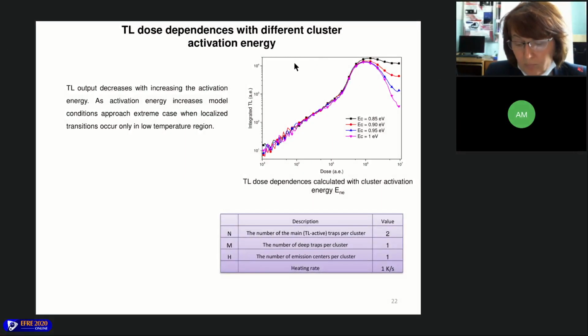The figure shows the influence of the activation energy of the cluster on the non-monotony. TL output decreases with increasing activation energy. As activation energy increases, model conditions approach the extreme case when localized transitions occur only in the low temperature region.